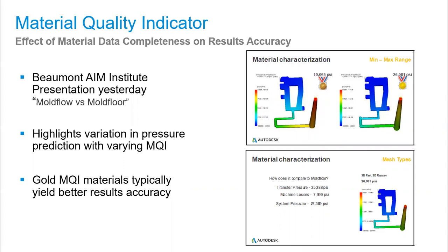Jen and Jason from the AIM Institute had talked about the importance of material characterization, and they did show that they chose two of the same grade materials, and one had a bronze level MQI and one had a gold level MQI. And you can see the drastic differences between the pressure prediction. So we see about 10,000 PSI and 26,000 PSI. So you kind of scratch your head when you get some of those results and figure out, well, which one's right. Well, they actually ran that one on the floor and came back, and obviously the one that had more accurate material data in this particular case gave them the most accurate results, within essentially 1,000 PSI from the machine that they had,